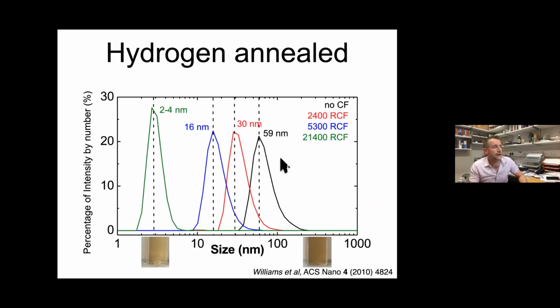If you do that, even after just heating in hydrogen, they already break down a little bit into smaller particles. But when you centrifuge out the big fellas, remember what I said about DLS? If there are big particles, you can't see the small ones because the intensity is all coming from the big ones. You just need a big centrifuge. And then now you have a really nice solution of a few nanometers.